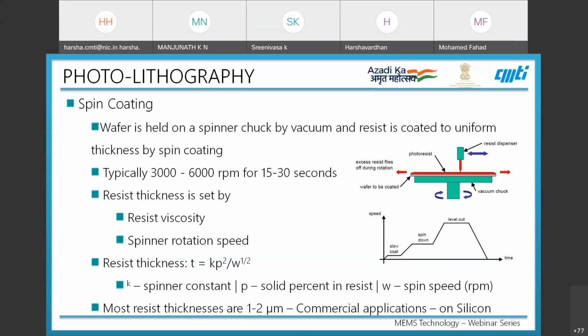Spin coating is a method where a wafer is held onto a spinner chuck by vacuum, and the resist is coated to uniform thickness by rotating the stage. Typically, the RPM used varies between 3000 to 6000, and the time duration is about 15 to 30 seconds. This process has to be optimized for a particular resist.